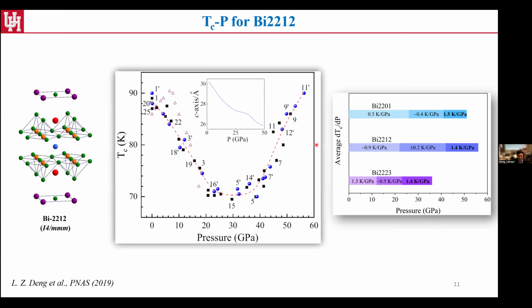Then we move on to the double layer Bi-2212. We see similar behavior, even though the first range is decreasing instead of increasing, and later the Tc didn't go up too high. But it does show that for all these single layer, double layer, triple layer Bi-based cuprates, you all have a Tc resurgence region and a pretty similar rate, 1.5, 1.4 Kelvin per GPa. So we would think there must be something universal here that is worth further exploring.